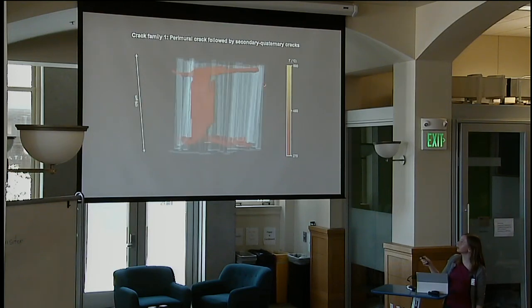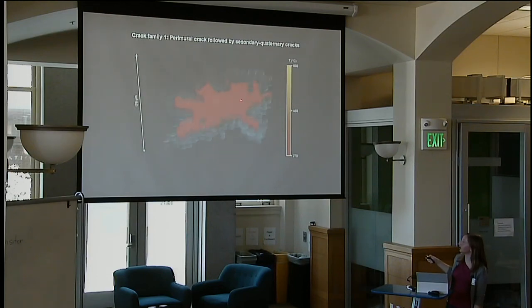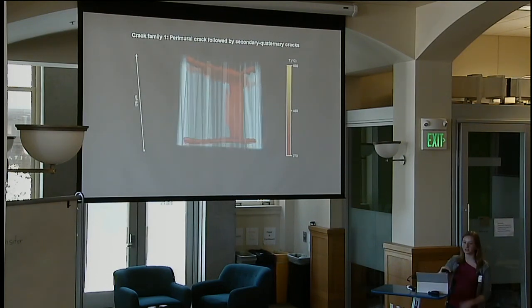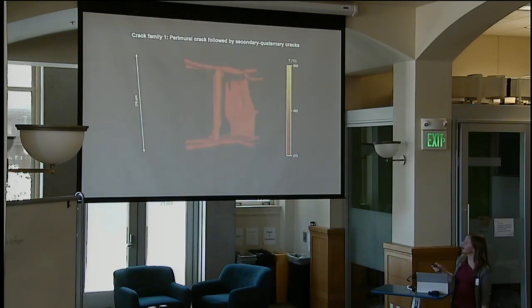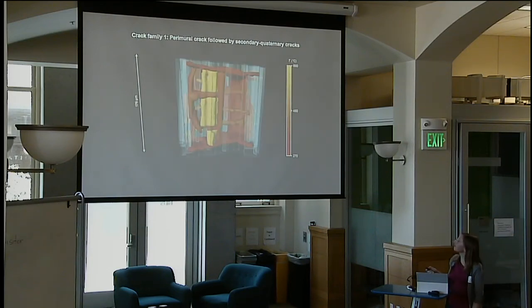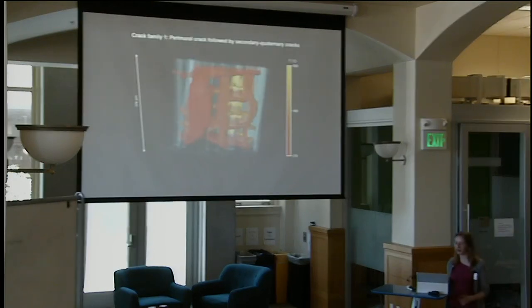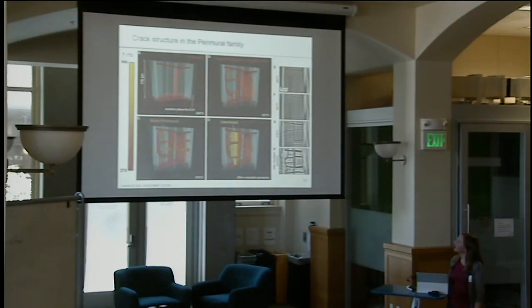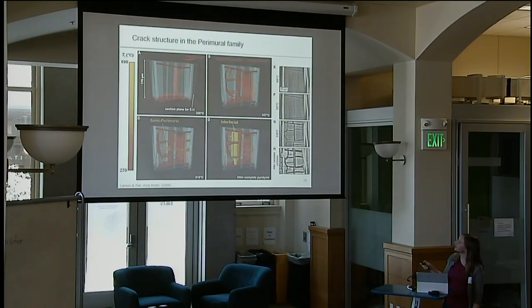These cracks are primarily perpendicular to the fibers. However, they often initiate at a fiber matrix interface, where they then travel along that interface and then kink into the matrix and spread out. At higher temperatures, these longitudinal cracks will then form. And then at even higher temperatures, we see the formation of what we've called semi-perimeral cracks, which are also perpendicular to the fibers, but only span a part of this region of matrix. And then finally, we might see the formation of interfacial cracks at even higher temperatures. So this is showing these 3D renderings at increasing temperature, showing the four different types of crack geometries we've identified within this perimeral family.